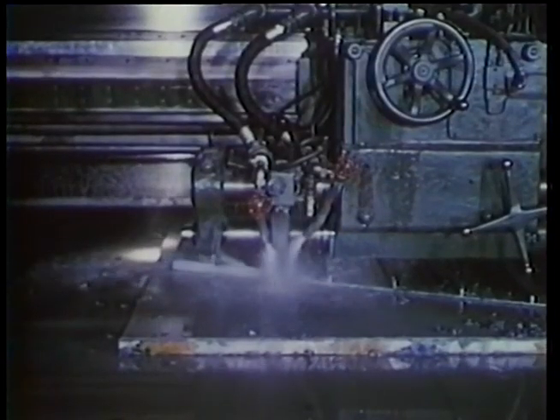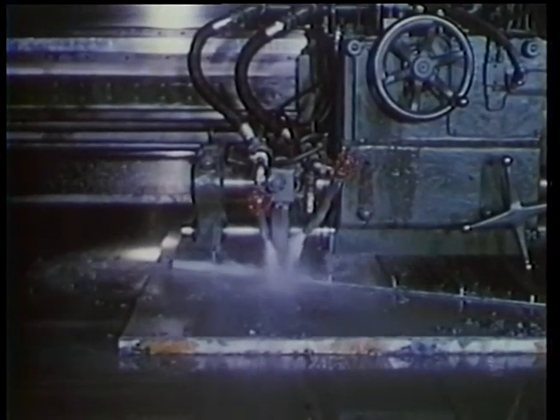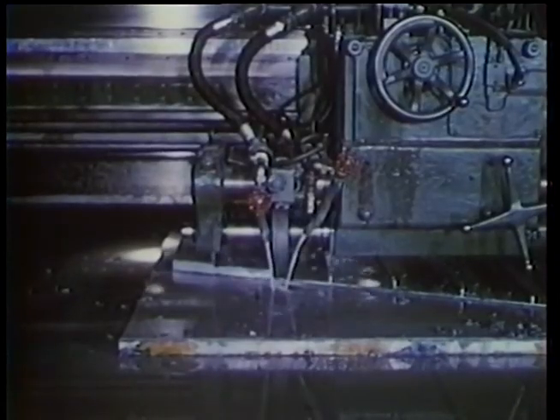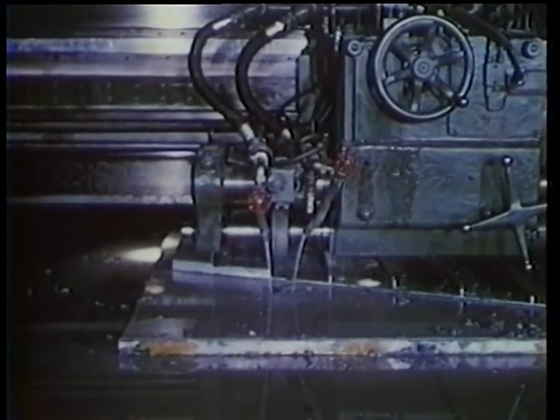This 200-ton skin milling machine started operations in September of 1956 and is the first of its kind in Canada. Used to machine integral wing skins and stringers from solid metal, this machine is guided by templates and can reach speeds up to 100 inches per minute on straight-through cuts. For conventional milling cuts, this speed can be increased to 160 inches a minute.